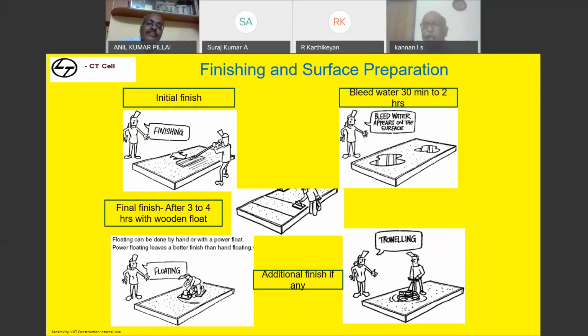Okay. I'll tell you how to deal with that. You have to send the mason back after 3 to 4 hours with a wooden float and tamp the entire surface. It is not only the cracked surface; the entire surface you have to tamp only with the wooden float, and finish it in a circular manner so that the concrete surface becomes rough. If any other finishing needs to be done, like a power trowel finish, you can do it.